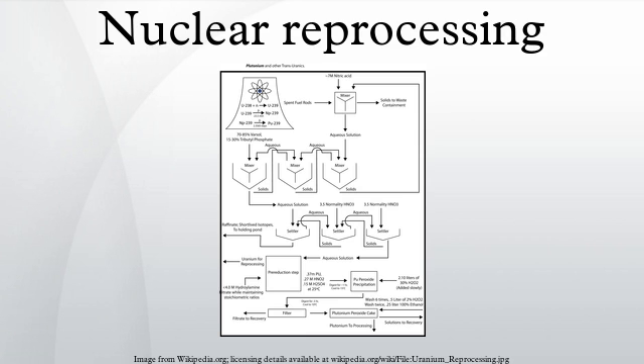Volatilization in isolation, simply heating spent oxide fuel in an inert atmosphere or vacuum at a temperature between 700 degrees Celsius and 1000 degrees Celsius as a first reprocessing step, can remove several volatile elements, including cesium, whose isotope cesium-137 emits about half of the heat produced by the spent fuel over the following 100 years of cooling. The estimated overall mass balance for 20,000 grams of processed fuel with 2,000 grams of cladding is given, though tritium is not mentioned in this paper.